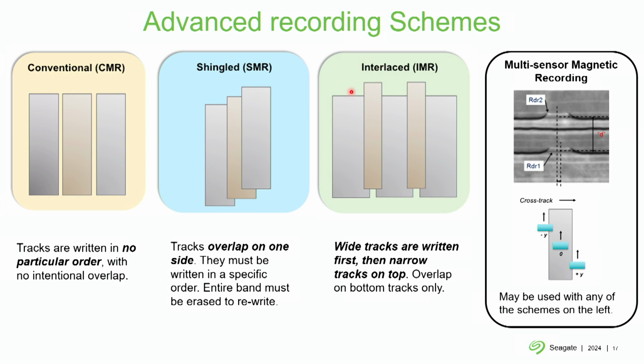And then there's this other idea called interlaced magnetic recording, where you have two different types of tracks. You have wide ones that are written first and narrow ones that are written in between the wide ones. And the idea here is that I'm writing a very wide track, so I can make the bits actually small for these wide tracks because I have so much better resolution in the writer when I'm writing at higher temperature. And then you have these narrow tracks on top that don't see any influence from adjacent tracks because they're written after the wide ones and they're far away from the other narrow ones. This is an even more complicated system because you can't really erase the wide ones anytime you want. So this is not yet in a product, but it provides even more areal density gains relative to shingled.